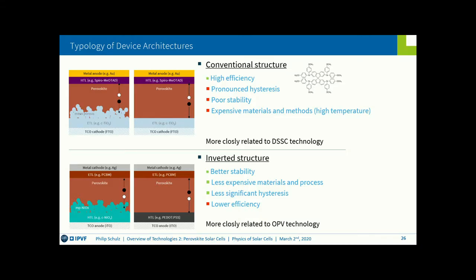Now there are two differentiations to be made when we talk about the device structure. We have the conventional perovskite structure derived from the DSSC technology. It shows high efficiencies, but also we observe oftentimes pronounced hysteresis. The stability is not as good. Back then it was really bad, but nowadays, and I will give an example later on, we can make perovskite solar cells that are stable for over thousands of hours, but maybe not years yet in the field. And also the materials were a little bit expensive. You need to go through a high temperature step in order to make good titanium oxide.